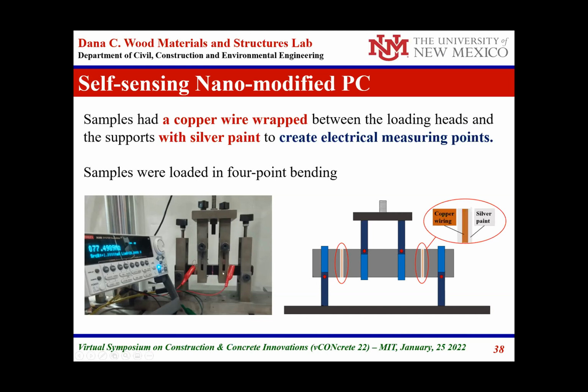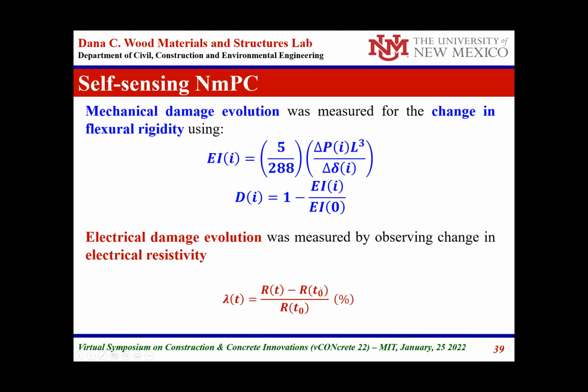So with a source meter, we are basically measuring the change in conductivity as we do cyclic loading. From the measurements, we can measure the change in load displacement, and from that we can infer the modulus of elasticity, or the stiffness of the polymer concrete, and the mechanical damage happening during the cyclic loading.